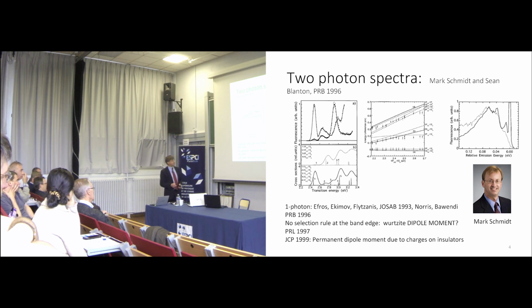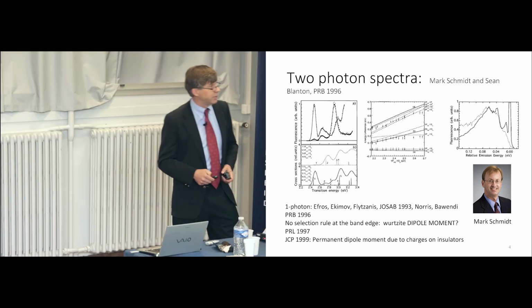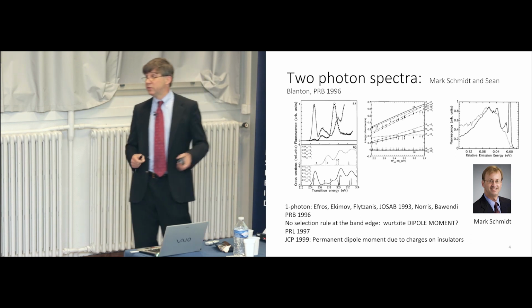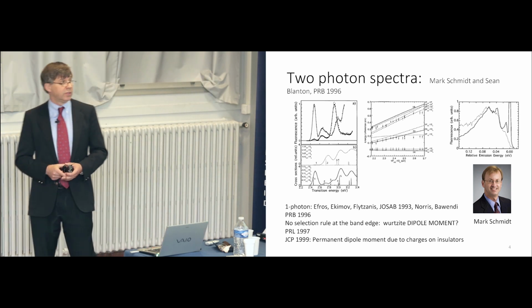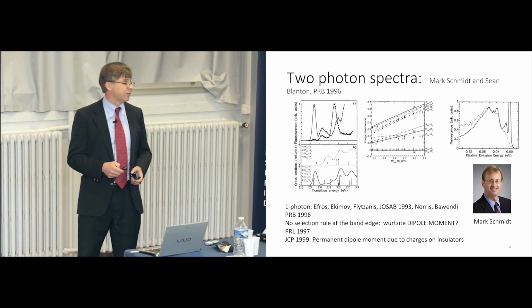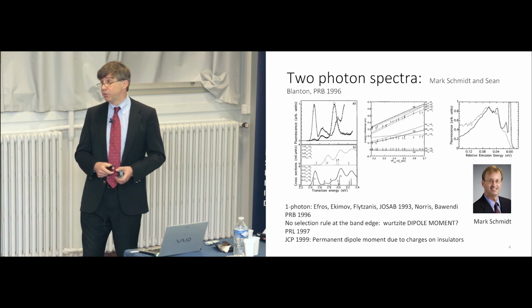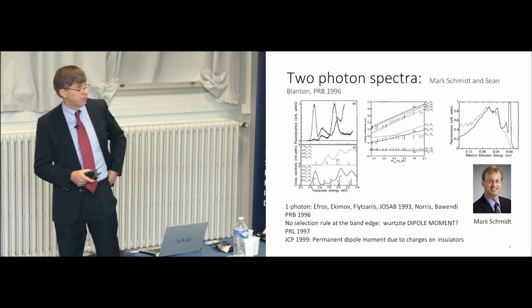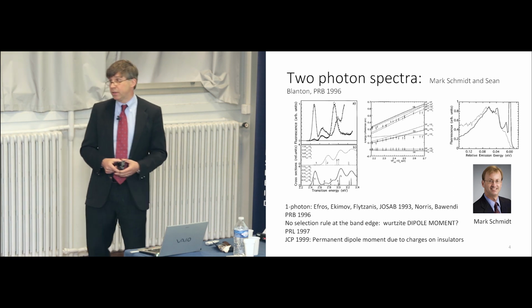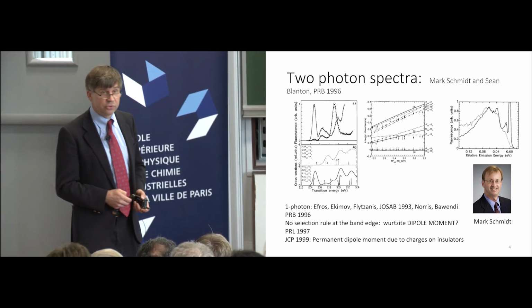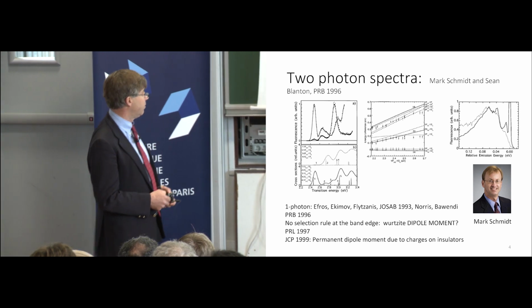So the lack of a clear selection rule led us in some other direction. We thought maybe there's a dipole moment in that structure. And so we looked for the dipole moment. That was one of Sean Blanton's successes, to be able to measure a permanent dipole moment in those small particles of cadmium selenide. And initially we thought it's simple, it's just a wurtzite structure, so it is polar, it has to have a dipole moment.